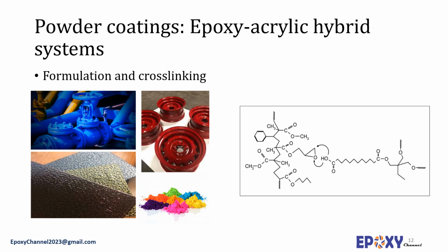These systems require a low temperature of 114 to 160 centigrade for stoving and are suitable for automotive original equipment manufacturing or OEM coatings, and especially as clear coats, in which the higher temperatures may adversely affect the other layers of the automotive coating system. Aliphatic or cycloaliphatic polyanhydride cured epoxy acrylate coatings exhibit excellent weather resistance, high gloss, and hardness with relatively good yellowing stability, features required for weatherable top coats, for example, for automotive or OEM clear coats.